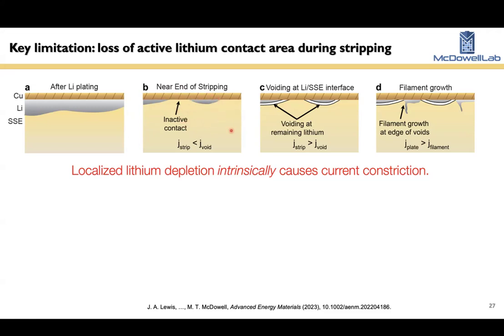This causes high local current densities, which necessarily causes voids to eventually form at these remaining islands. So you'll have some voiding at these remaining regions. Then when you reverse the current and grow lithium, these voids again cause the current to be concentrated, and that's where you may grow filaments at the edges of these voided regions.